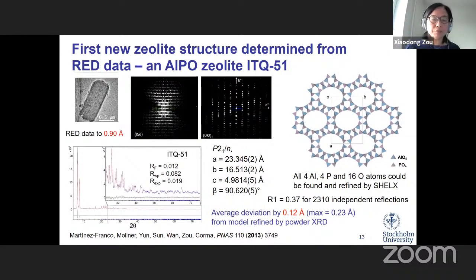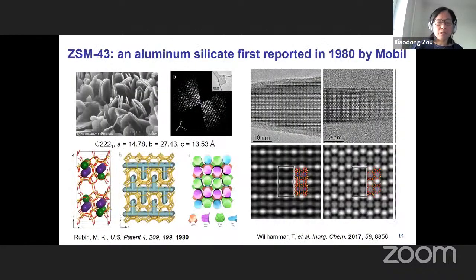And this was the first zeolite structure we determined using rotation electron diffraction. It's an aluminum phosphate. As you see here, this is the data we show. And it contains large rings. We usually count the ring size. This is a 16-membered ring, a 16-ring. And the structure was solved basically from electron diffraction.